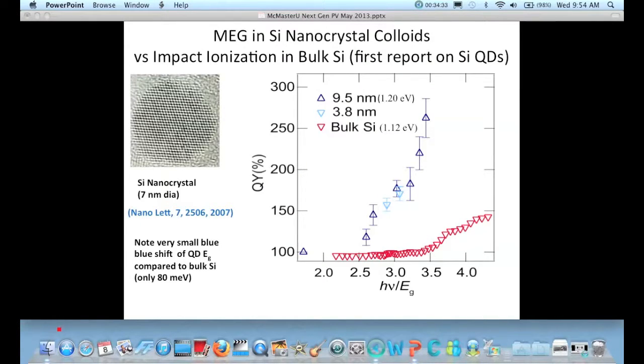Another controversy that arose in those days was that the people who were skeptical about this effect, this usually happens in science when there's some new phenomenon that's reported, there'll always be, and that's good for science, a part of the community that's skeptical, and you have to get reproducibility in these experiments. But they also said that in their experiments, when you plot the quantum yield versus absolute photon energy and compare bulk to quantum dots, the data fall on top of each other. But that's not the right way to do it, because you need to divide by the band gap to tell you how many band gaps of energy you have being absorbed. That's the more fundamental parameter as opposed to absolute photon energy.